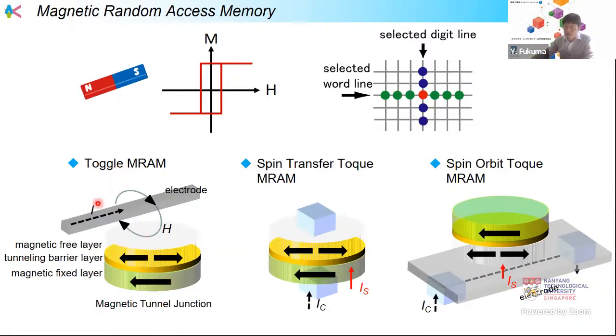In the case of this kind of writing scheme using an external field, there is a problem with the operation margin for making a high density random access memory. That's why the writing scheme has now changed to spin transfer torque. With spin transfer torque, we can inject the spin current from the pinned layer into the free layer. Then the magnetization direction changes.